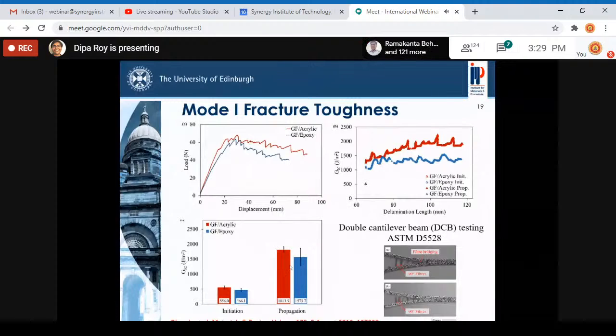It means that, as we expect, the fracture toughness of the acrylic composites is quite good, as we expect in case of thermoplastic composites. And this was observed because this is a quite slow strain rate of testing. The strain rate is quite low. We use about, I think, 2 millimeter per minute speed, which is quite low. And with that kind of low speed of testing, acrylic behaves in quite a ductile way. So that played a big role, and we saw a big advantage of this higher fracture toughness.